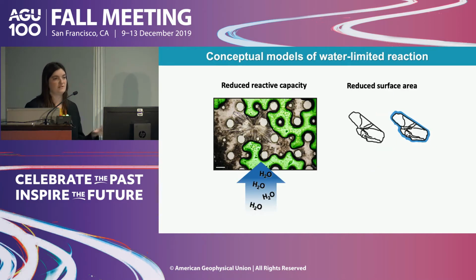Now, there are a number of potential explanations for a reduced amount of reaction at low water saturation. For example, we may have an effectively reduced reactive capacity, so a lower amount of total reaction possible, as we just don't have enough water to facilitate these reactions. We may also have an effectively reduced reactive surface area, as some grains may be less exposed to the reactive fluid than others. This would reduce our effective surface area and thus our bulk or effective reaction rate.